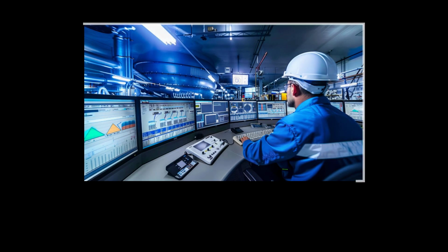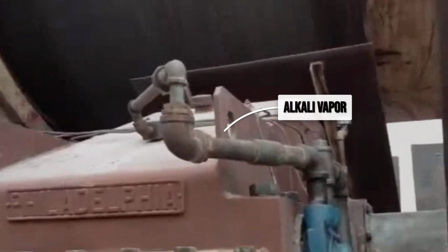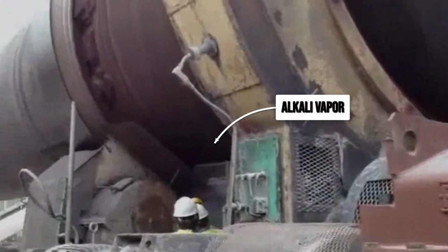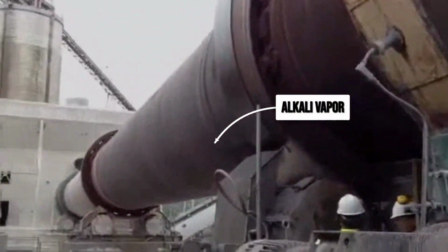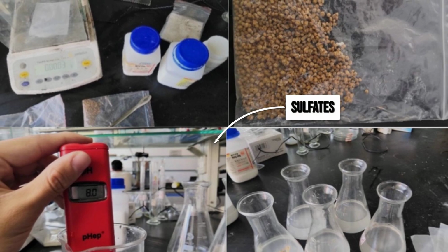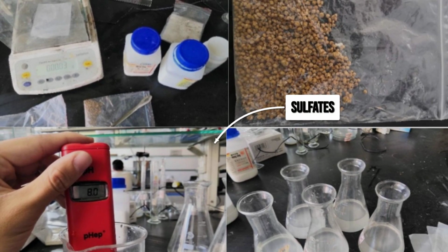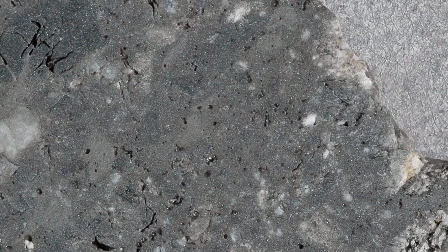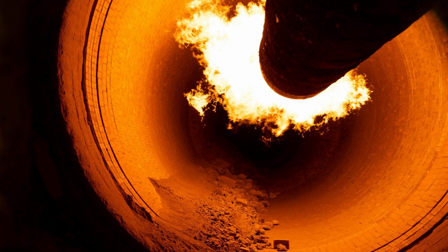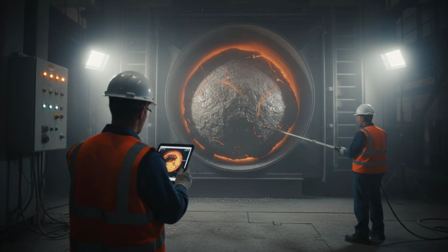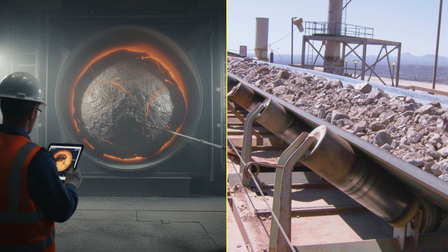The volatile cycle drives this buildup. As kiln gases carry sodium and potassium vapors forward, they cool and condense, binding with sulfates and fine meal to create a sticky, low-melting crust. If left unchecked, this crust can balloon into a full blockage, threatening to choke off clinker flow entirely.